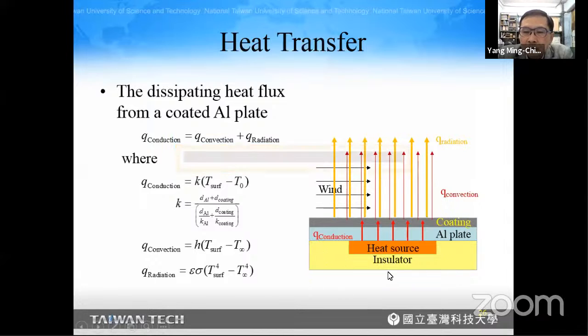In our experiment, the heat flux dissipated from a coated aluminum plate is illustrated in this video. There is the heating source, and on top of that is an aluminum plate, and on the surface of the aluminum plate is a layer of coating, and the heating source is insulated with an insulator. We use cork as the insulator, and the heat transfer occurs.